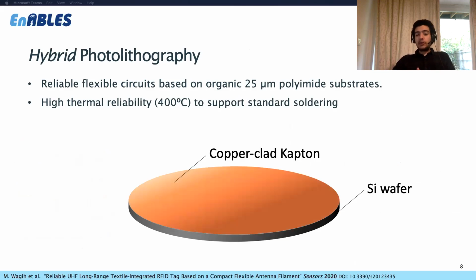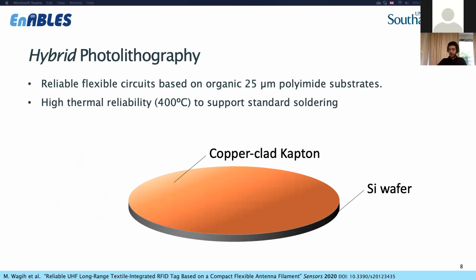What we came up with to avoid some of the problems of printing is what we call hybrid photolithography for low-cost flexible circuits. So we've adapted some of the photolithography methods used in nanofabrication and printed circuit boards to suit flexible circuits. What we start with is commercially available polyimide substrates, which come with a smooth homogeneous copper layer on top, which we can then etch.